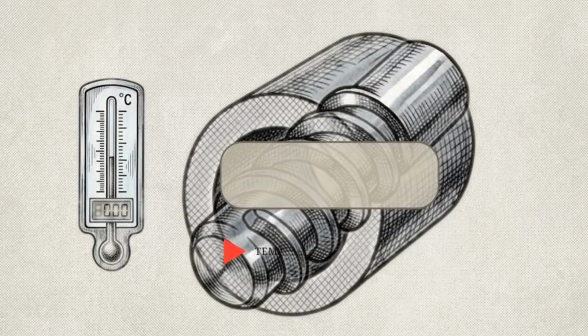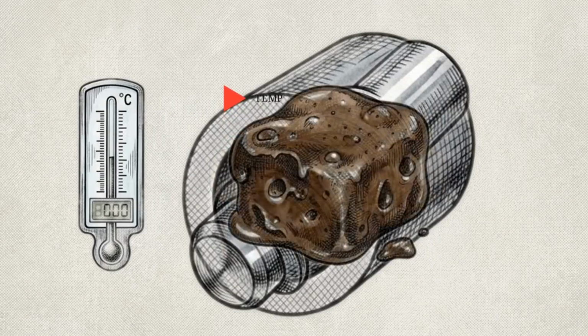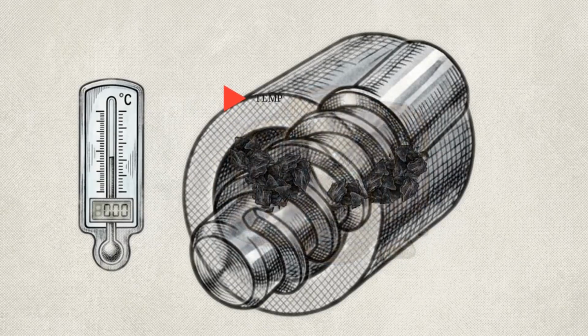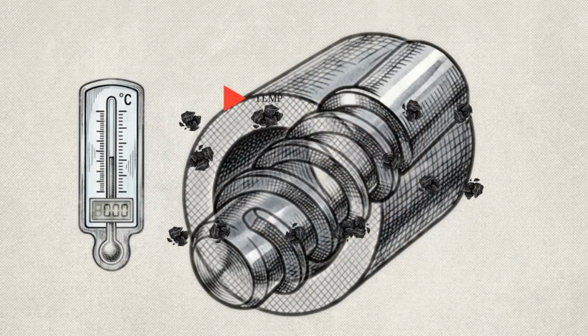Step 1. Check your control panel and lock in the current, safe processing temperature for your specific flexible material. On this control panel graph, the temperature line remains flat. Do not spike the heat to force the material out faster. If the temperature exceeds the material's tolerance, the elastomer burns and bakes a hard layer of carbon directly onto the metal surfaces of the barrel.